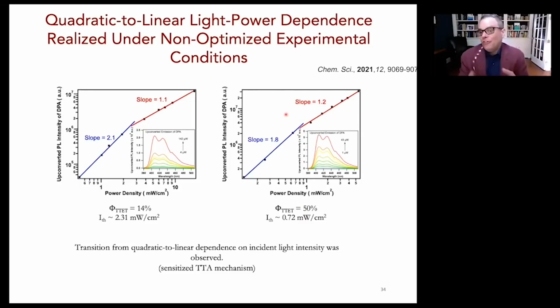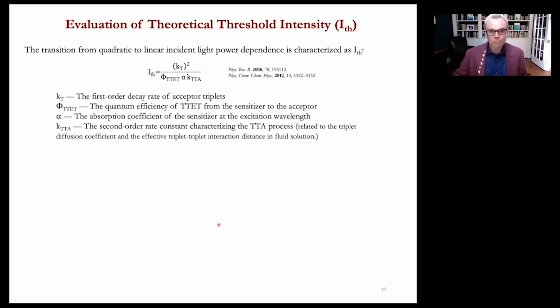And remember, when we do this and everything is optimized, it's over 95% efficiency. So that was why we couldn't actually see this turnover point or see any quadratic dependence whatsoever. So clearly, this is a sensitized TTA mechanism with all of the donors and acceptors we're using here.